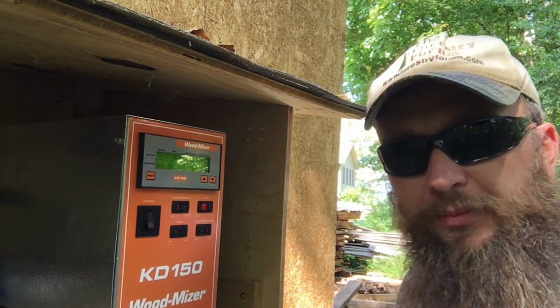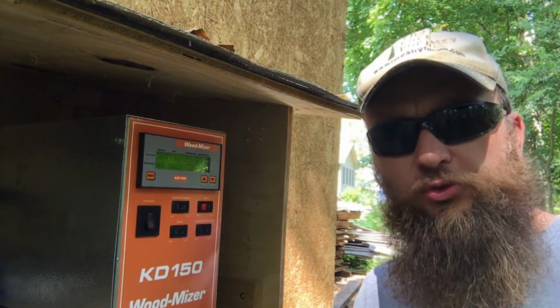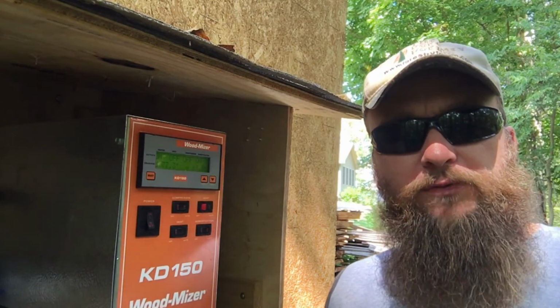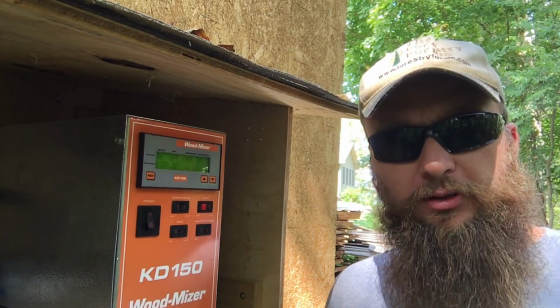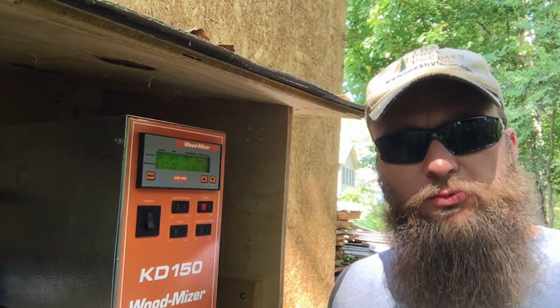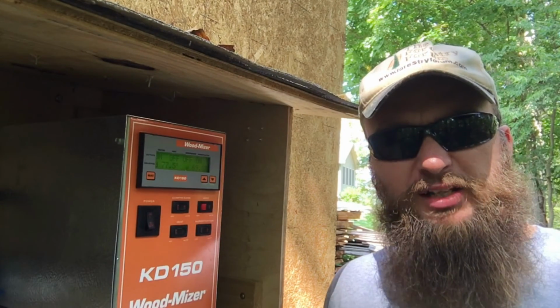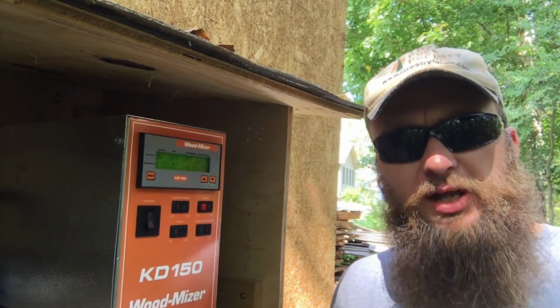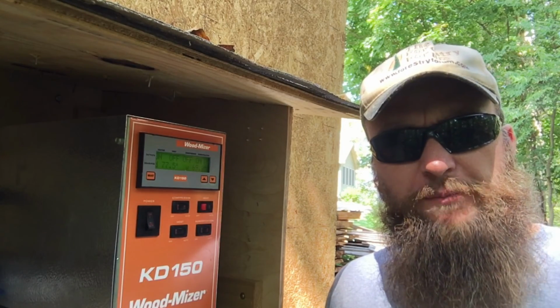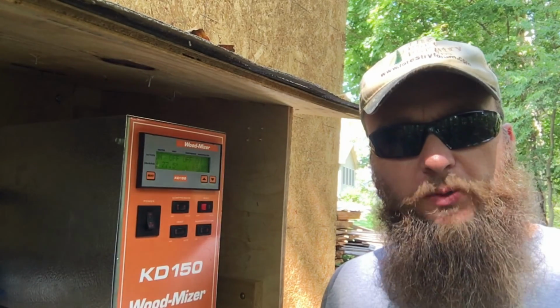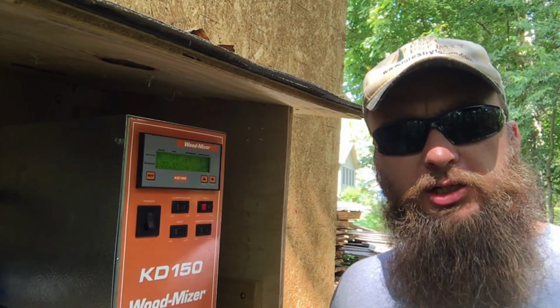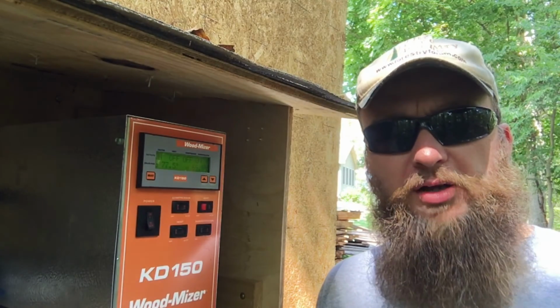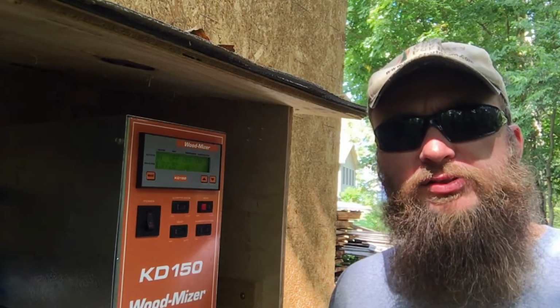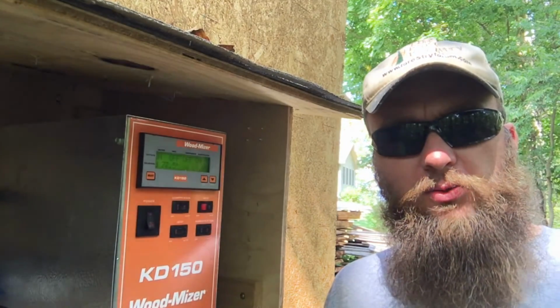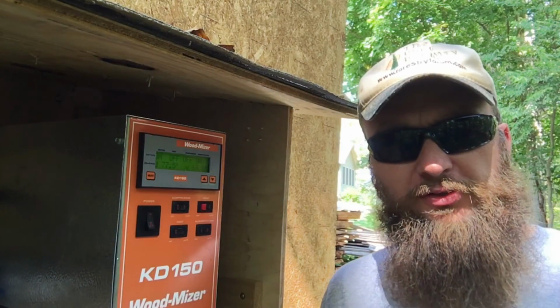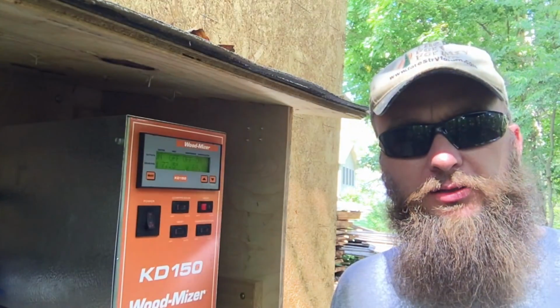By setting those parameters, 125 dry bulb and 75 degrees wet bulb, you're essentially running this kiln what they call wide open. That's max capacity, and that's the way it runs, wide open. And by using air-dried lumber, you can do that. You can start right off by running it wide open. You don't need to work your way up to it. If this was green wood, you'd have to scale back a little bit because you don't want to get too hot too soon, because it's going to dry the wood way too fast. And when you're drying white oak and red oak and it's green right off the mill, you have to be real careful in those first few stages on how fast you dry it.